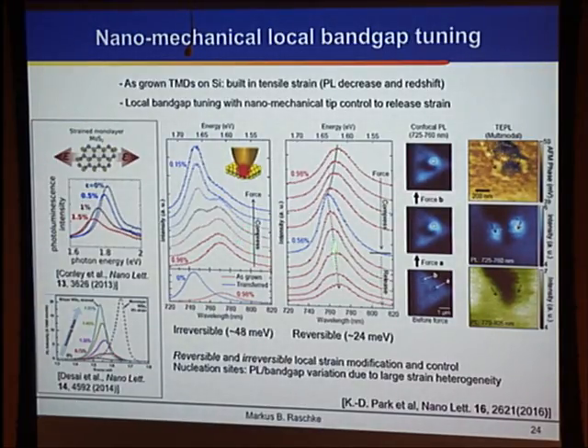And we can actually, from the exciton peak position, quantify the amount of built-in strain in these nucleation sites. And so this really allows us to control, through this nanomechanical interaction, both reversibly and irreversibly, the strain. And it really shows that these nucleation sites have the photoluminescence decrease, in this case, simply as a result of the variation of the band gap, and not because of ill-defined stoichiometry, as it was thought.